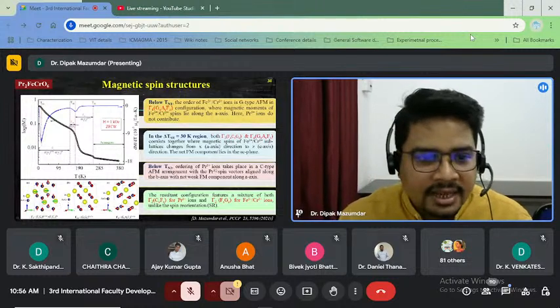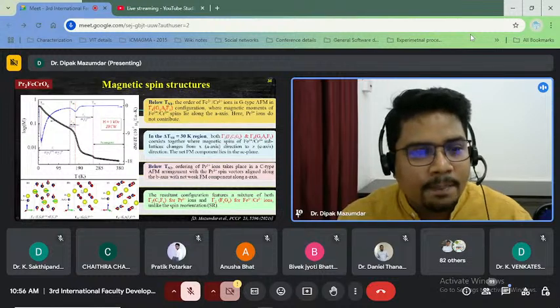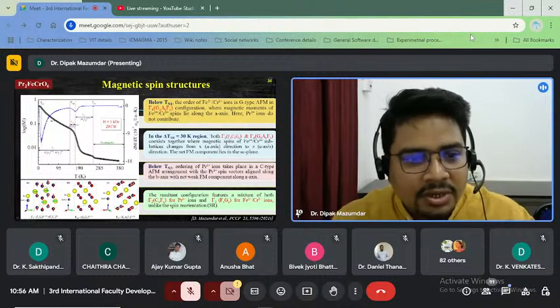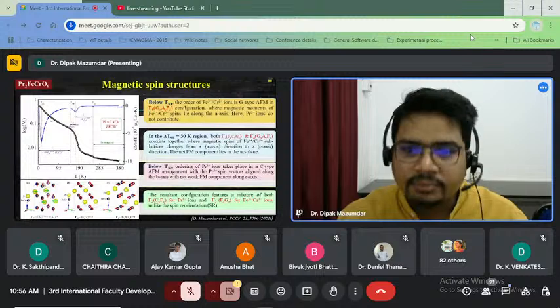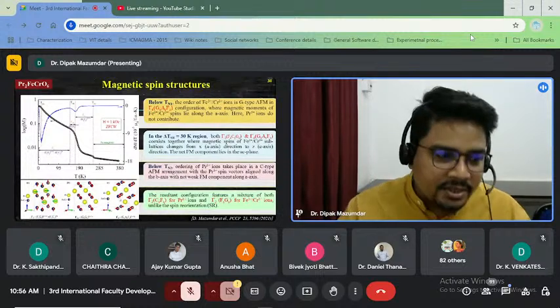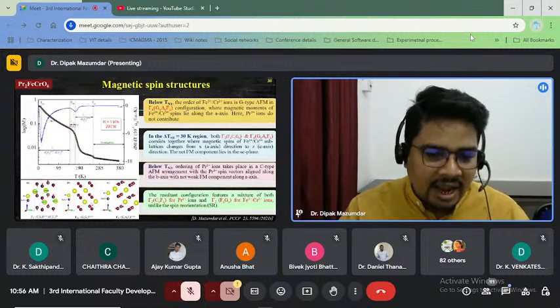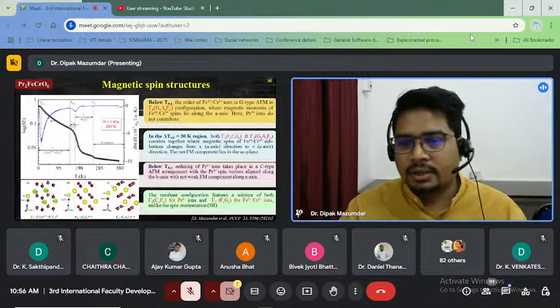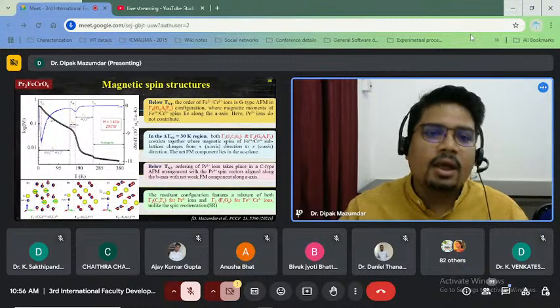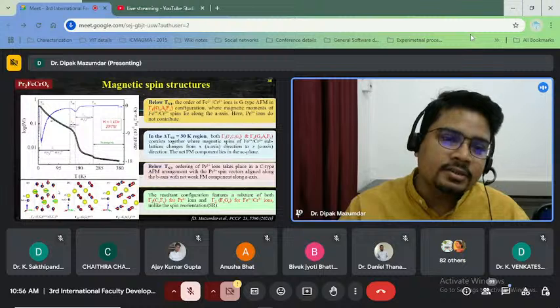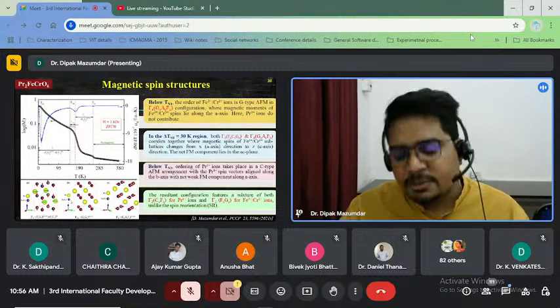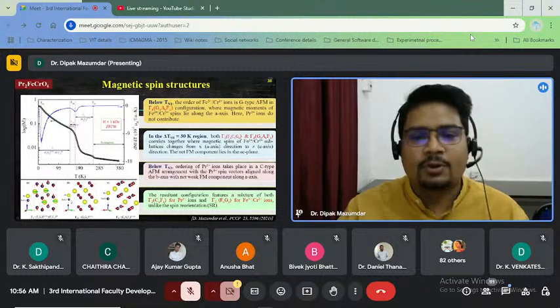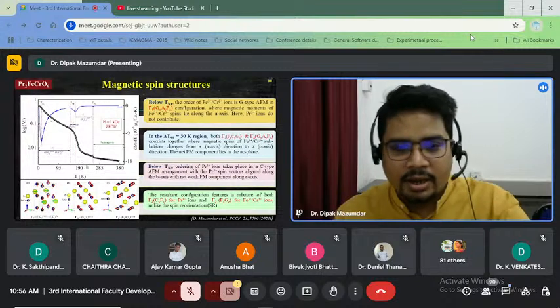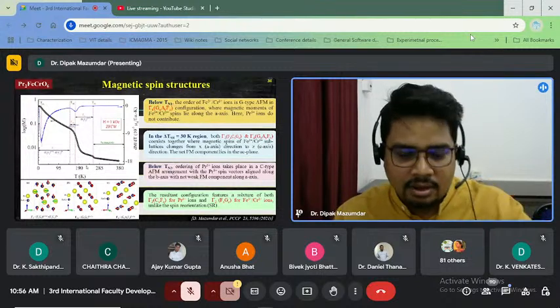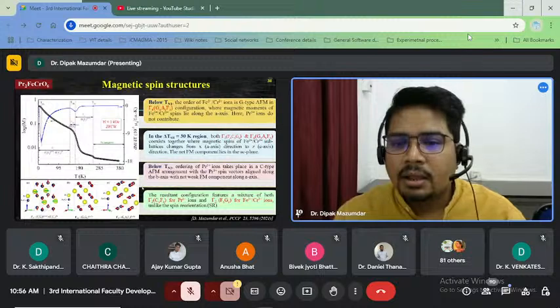And at the same time, praseodymium ions have already completed their spin orientation, so it is in the z direction. So this spin structure I derived for this compound in 2021, and after 6 months, a similar structure was experimentally described by Wang et al. So this was a good prediction for my purpose.